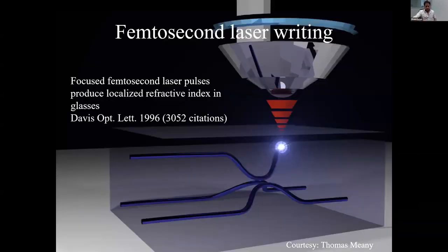So, a background on femtosecond laser fabrication. This isn't a new concept. It's been around since 1996. The first group to discover it, former collaborators of mine, were from the University of Kyoto, Davis and colleagues. They were the first to show that by focusing femtosecond laser pulses beneath the surface of a transparent glass, the light was nonlinearly absorbed, resulting in a permanent refractive index increase only within the focal volume.